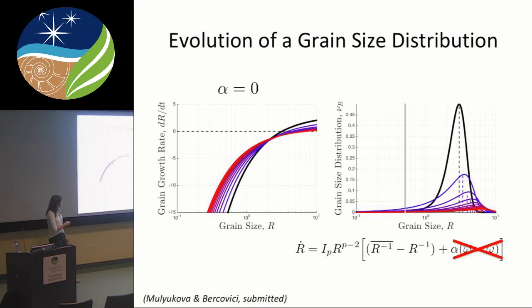When there is no effect of dislocations, small grains are shrinking, large grains are growing, and I should say, the colored lines tell you different time snapshots. Okay, so black is the initial state, blue is early on, and red is late in the evolution. So small grains are shrinking and large grains are growing, and the small grains are shrinking faster than the large grains grow. So effectively, this will manifest itself in the whole distribution being broadened and shifting towards larger grain sizes. So this is what is known as just continuous normal grain growth. Also, actual rocks don't have this nice Gaussian-like grain size distribution, but this behavior of shifting towards larger grains and broadening is robustly observed in the experiments as well. So this is just normal grain growth.